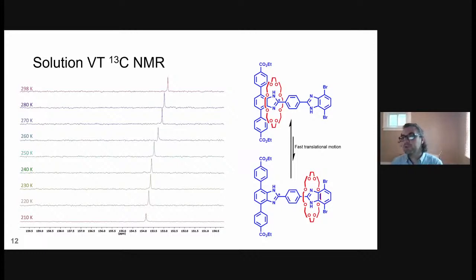So whenever we synthesize a new rotaxane, the first thing we do is we take the ester form before we hydrolyze it for making this carboxylate linker, and we characterize the dynamics in solution via variable temperature solution NMR, in this case carbon-13, as we have this carbon-13 enriched position here.